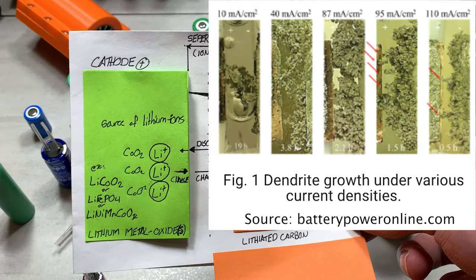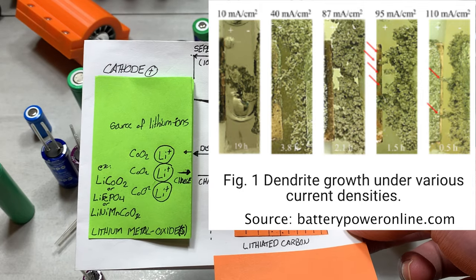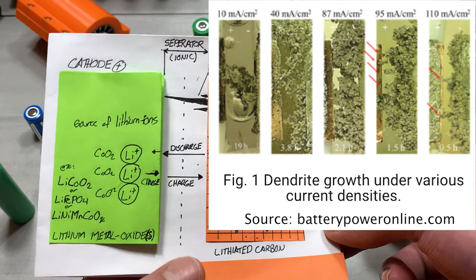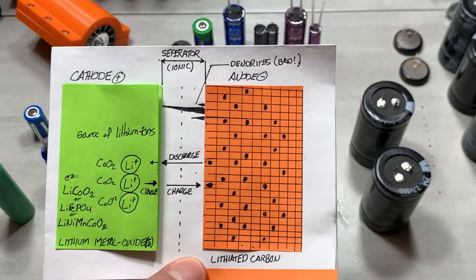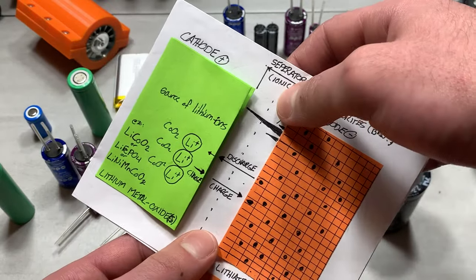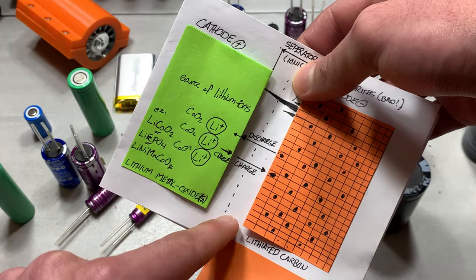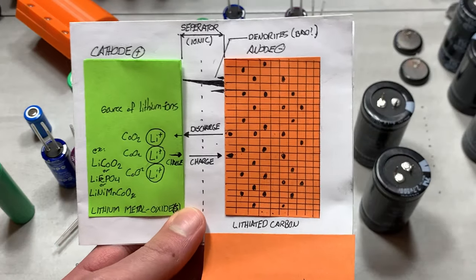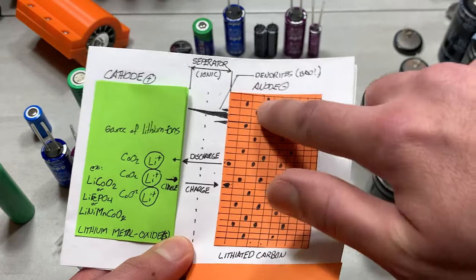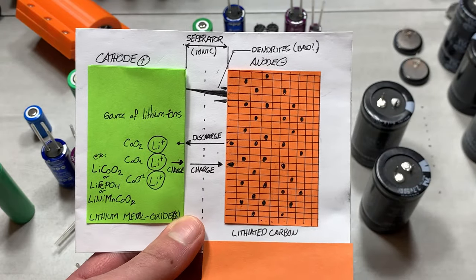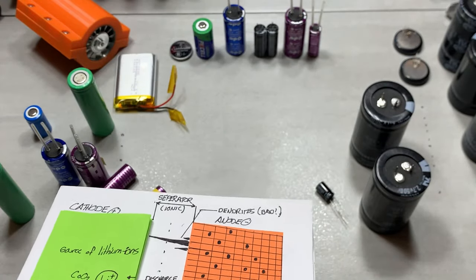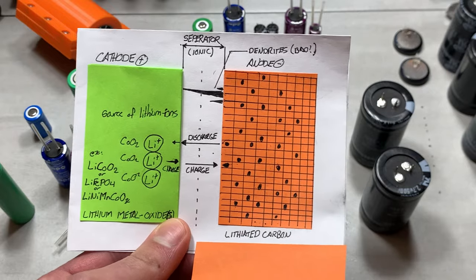They then have a picture where they compare the dendrite growth versus the current density, which, going back to my screen door analogy, is basically how much current you're applying. Now, this isn't really specific to the separator, but the separator would play a role in this, as would the surface areas of the anodes and cathodes, which then brings me to the supercapacitors and their internal construction.